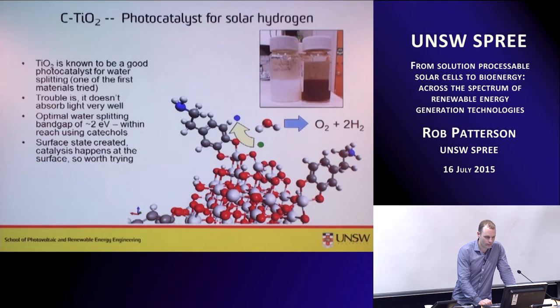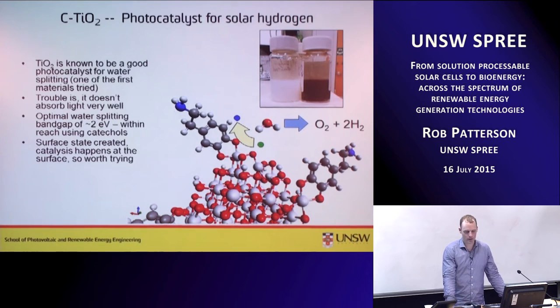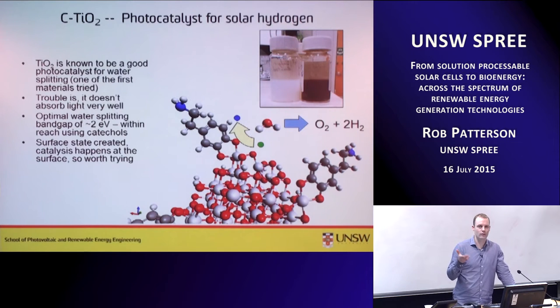So as a result of this, I initially wanted to try this material as a potential N-type material for nanoparticle solar cells, but I believe that transport out of this material is going to be very challenging because this defect state may be very strongly bound at the surface. So what would be potentially more feasible is to try a photocatalyst approach. Because catalytic reactions happen at the surface. Here you have a surface state with a strong dipole and maybe a 2 eV band gap. So you have the opportunity to apply this as a photocatalyst for splitting water.